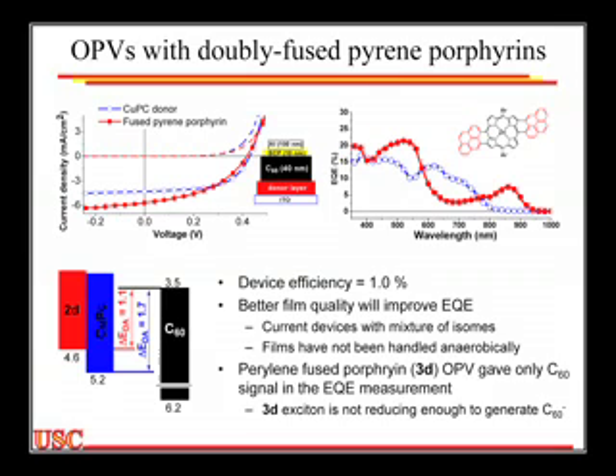So we've made solar cells with both of those, and before I show you the data, I would caution you that these are still the mixtures of 8 isomers, which isn't what we want. We've now scaled up and made about 3 grams of the perylene derivative, and we're recrystallizing trying to get pure isomers. But it works. It makes a solar cell. You can see that our pyrene derivative goes out to where the absorption spectrum says it should. We're tailing out to 900. This sort of shows you the comparison to CuPc. The efficiency for the device is only about 1%, and that's because our fill factor is relatively poor, and our exciton diffusion length is relatively poor because of the mixture of isomers.